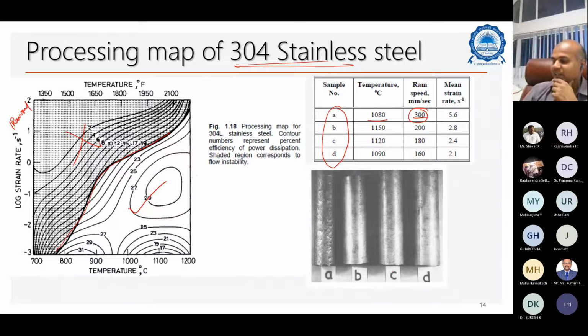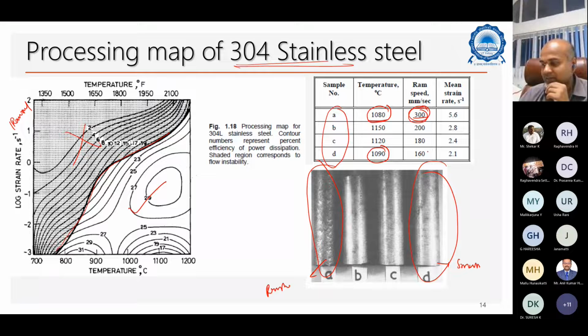A, B, C, D here, both are of the same initial dimensions. If you look at the surface here and the surface here, this surface is very rough. This is very smooth. The only difference is that you process this at 1080 and 1090. Both are more or less the same temperatures. Look at the rates. This is half of the strain rate that you're using. If it's 300 mm per second you're pushing it, whereas at 160 mm per second you are pushing it. You decrease the rate by keeping the temperatures the same for both of them, and you get a completely different structural response.